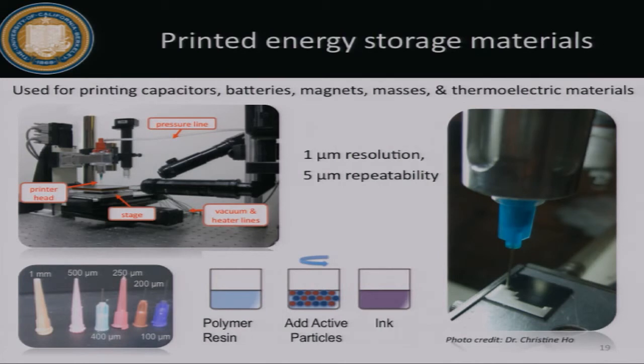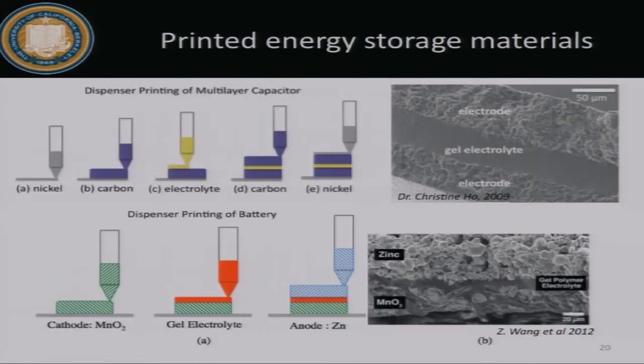So the way the printer works is it's a pneumatic printer, and you basically start with a polymer resin and add ground up active particles that are ball milled to whatever diameter you want, and then mix those together to create an ink. And that ink goes into a dispenser printer tip, and then it's pneumatically dispensed onto a substrate. And what's cool about this is you can use any active particles you want. So it can be, as I have up here, electrochemical materials, thermoelectric materials, magnetic stuff or just heavy materials. You can do any. It's a very, very flexible system. And you can print in different patterns and on any substrate. So it's a very interesting and versatile setup.